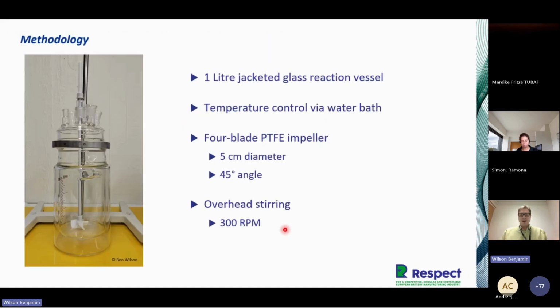So we're talking about hydrometallurgy here. As was explained very nicely in the first two presentations, this is atmospheric, on a lab scale. A 1 litre jacketed glass reaction vessel, with temperature control via a water bath on the outside. There's a 4-blade PTFE impeller with a 5 centimetre diameter and a 45-degree angle, providing the agitation that's quite critical for these kinds of things. In this case, the agitation was provided overhead at 300 RPM.